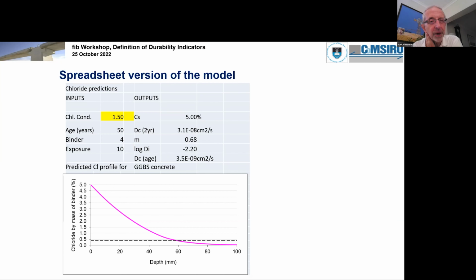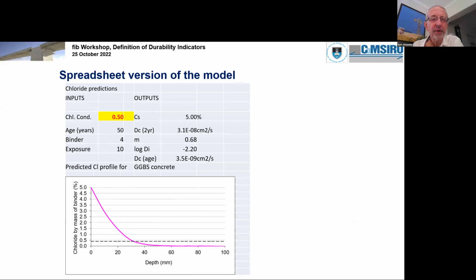And here you can see a chloride conductivity of about 1.5 millisiemens per centimeter and a 5% surface concentration at 50 years would give those parameters as we have there, different diffusion or exposure types. And this is a ground granulated blast furnace slag concrete. So you can see there that the typical 0.4% limit is achieved at, say, around 60 millimeters of cover. That's at 1.5. If you then reduce that chloride conductivity to 0.5, a much better quality concrete, so now you've got a much lower water binder ratio, then you can bring that down to, say, half that value, about 30 millimeters. And so here, by improving the quality of the concrete, you can get a much lower value for that profile, and you would need a lower cover to achieve the same life.